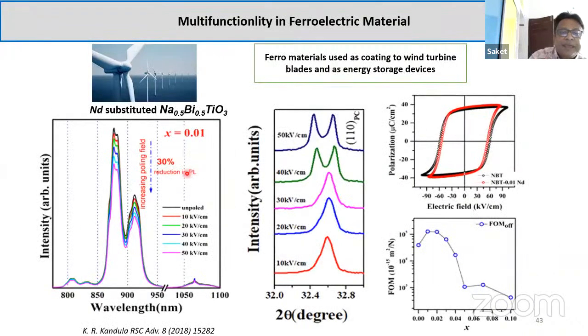Another thing in this system: we have substituted the rare earth at the bismuth site, with a small percentage of Nd, 0.01, very small. Why very small? Because we don't want to change the polarization. We want to retain the piezoelectric characteristic and introduce optical activity. Here you see the unpoled sample, and when you pole it with different electric fields, quenching of the PL emission happens with increasing poling field.